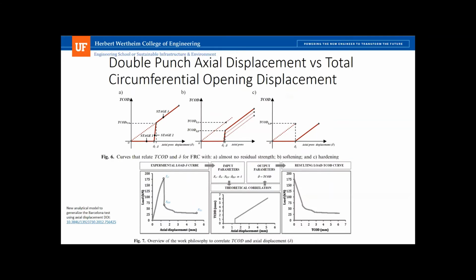So one of the things that was realized in this testing in Spain was that instead of measuring the circumference, you can get similar type of information by just measuring the axial displacement of the machine. And so you get a problem in plain concrete or concrete that's strain softening where you get basically no displacement measured by the extensometer in the circumference until you get a crack that forms.